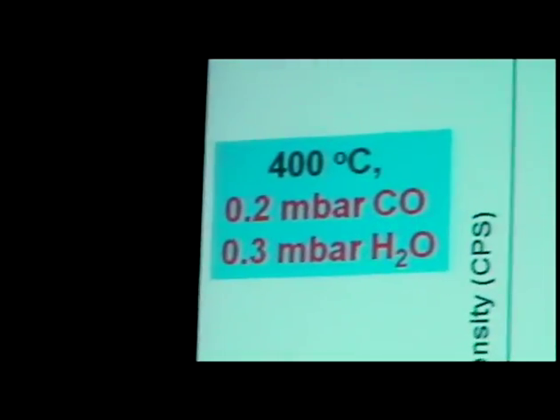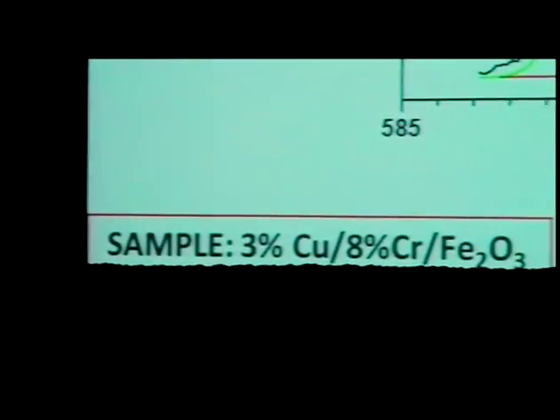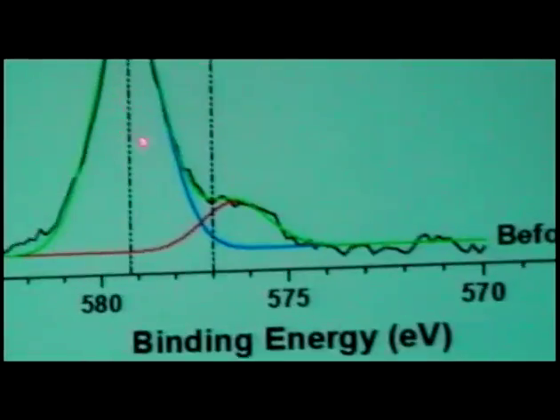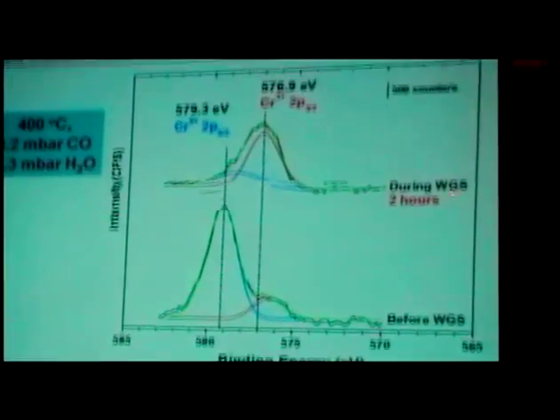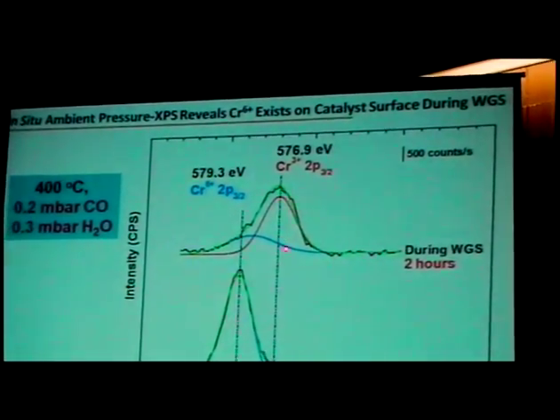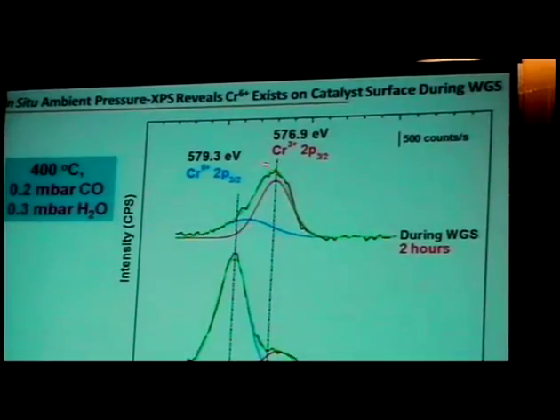The last part I want to talk about, this is more recent work, is copper promotion. It was discovered a few decades back that the addition of copper further enhances the activity, and so we want to understand what happens. This is again an in situ ambient pressure XPS experiment. And this is the starting material, chromium-6 with a little chromium-3 on the surface. And during water gas shift, you see again this chromium-6 present and